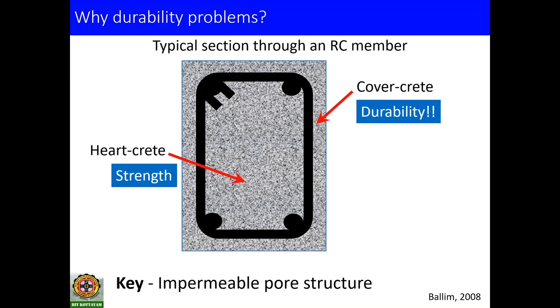And see why the durability is happening. Many of you might have attended some of my webinars, and this is a slide which my professors and I show many times, because this is the crux. We call the inner chunk of concrete the heart of the concrete, or the heartcrete, and the outer zone concrete is designated as the covercrete or the cover zone concrete. The inner chunk or the heartcrete is responsible for the strength, whereas the durability is obtained from the cover zone concrete. And there the key factor is the impermeable pore structure that we obtain in the cover zone concrete.